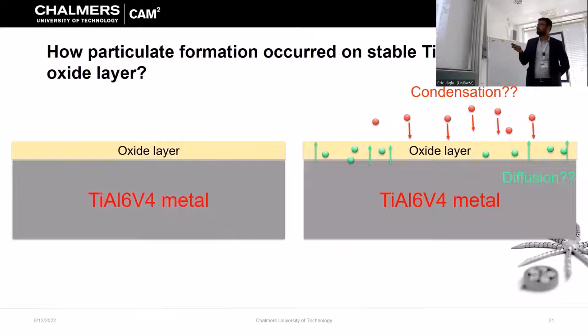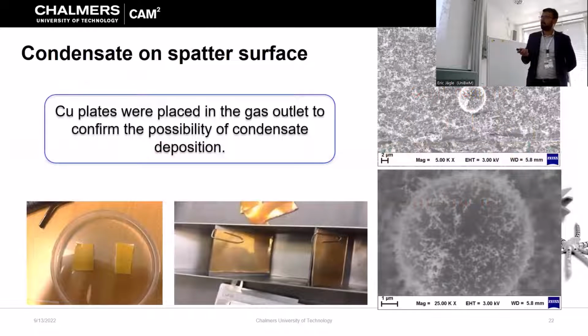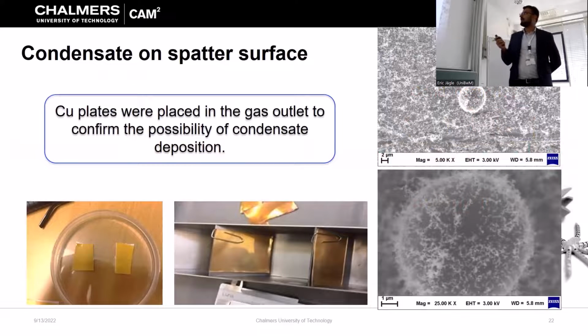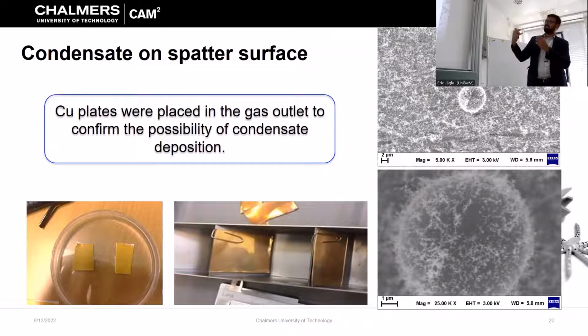So there were two options there, condensation or diffusion. Condensation is happening from the melt pool, vapors are going and depositing on the spatter surface, which have gathered in the gas outlet. And the second option was diffusion, like atoms are going through this stable oxide layer. To confirm that, we did an experiment where we placed copper plates in the gas outlet and tried to capture the condensation, analyze it, and compare it with the spatters to see if it is the same or different.